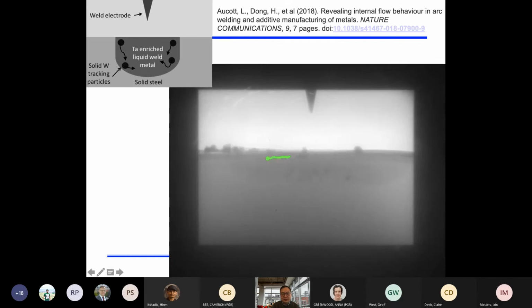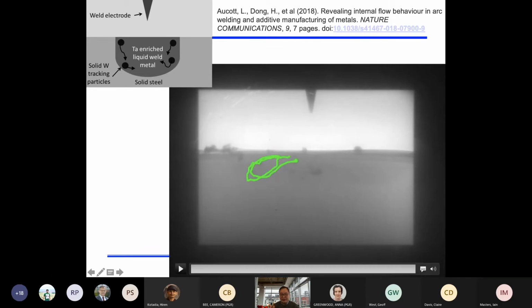After we get this raw image, we use an image processing method to trace the individual particles over each frame. The tracing took us probably more than half a year to figure out, how to trace individual particles inside the pool and then work out the average speed or the maximum speed of these internal flow streams. This is the way we trace the particles. So we have tungsten particles inside the liquid pool, and we trace the individual paths. By doing this, we are able to see the individual flow streams inside the weld pool.